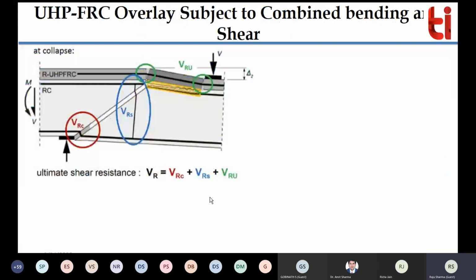Now how does it actually work? Earlier, your concrete basically had shear resistance VRC. So total shear is equivalent to VRC, concrete, plus steel, and there is a new component that occurs when you lay, as you can see in the top of this figure, the UHPFRC along with the reinforcement. So on the top surface you laid the UHPFRC along with the reinforcement. So there is a new resistance that exists because of this material, and we added it as VRU, right? VRU is the new resistance that exists because of the UHPFRC.